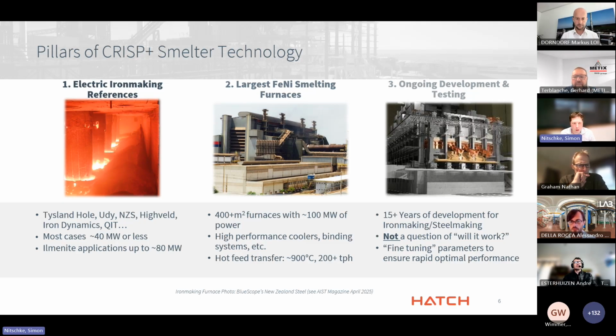From an equipment technology and design perspective, we've got industrial commercial scale demonstrated in adjacent industries already at the scale necessary for ESFs. I mentioned in non-ferrous, we've got industrial examples which are much closer to that necessary scale at almost 100 megawatts today. And they're physically at the geometry that is required for what we see as that commercial scale CRISP+ furnace. And it's really this that gives us the confidence that the equipment technology itself is ready to support that genuine blast furnace replacement. And particularly when you start to consider that a lot of that key componentry around the long campaign life that will be necessary on ESFs is already incorporated and demonstrated on those very large non-ferrous furnaces, including the cooling elements and the active lining system.